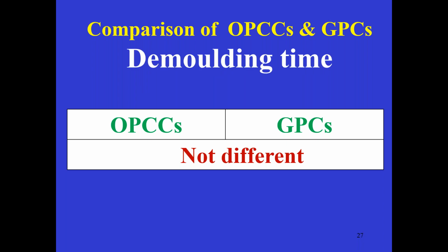That's all. And demolding time is not different, but it can be thought of as better also, because Portland cement can also be demolded within 1 day. Some Portland cement is able to be demolded within 4 hours. The same time can be achieved with geopolymer. So on the whole, we can say demolding time is not much different, provided our formulation is correct. Otherwise, the original formulation required 24 hours of keeping in the mold, then putting into the oven, and only then was demolding possible. Now, in the present work, what we have done and many others are doing, that handicap is removed.